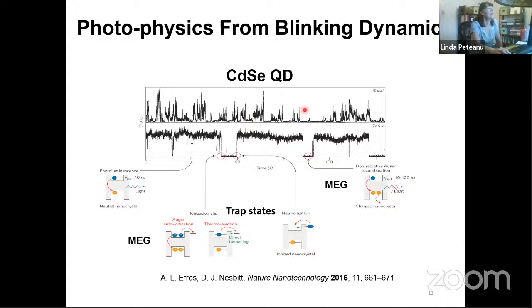This shows a bare quantum dot. This shows one that's been passivated so that it shows more emission with fewer dark spots. Now, obviously at high count, you're getting luminescence, you create an electron hole that re-radiates back down to the ground state. When you have dark spots, basically that can indicate a number of things. It can indicate energy transfer to a trap on the surface. It can indicate that you have, in fact, formed two excitons and you have an Auger process that's bringing you down to the ground state non-radiatively, or other forms of non-radiative recombination.